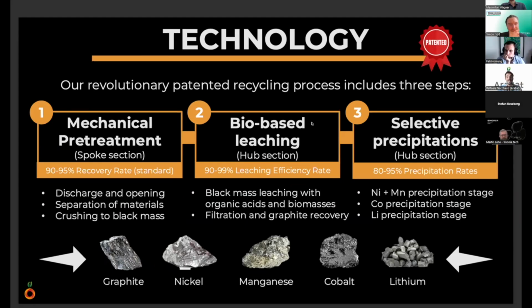Our bio-based leaching, a chemical treatment, where we put our black mass into a reactor in contact with water, organic acids like citric acid, with low molarity and concentration, and this homogeneous and heterogeneous mix of biomasses like simple orange peels from, for example, the orange juice production sector, or artichoke leaves from agriculture, and other biomasses that include reducing sugars and other specific substances that cooperate with the organic acids to lixiviate the black mass and put the raw material ions into the solution.